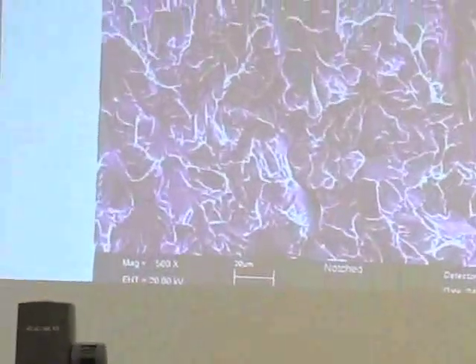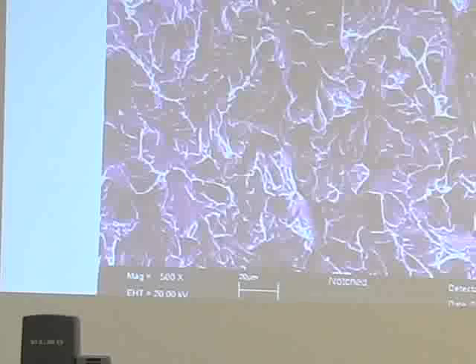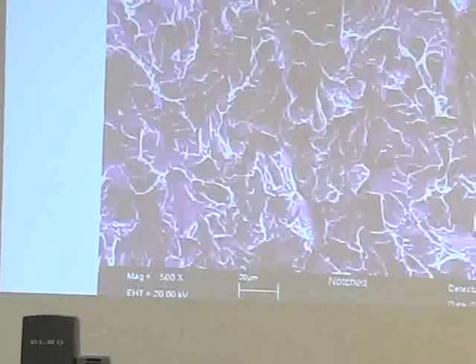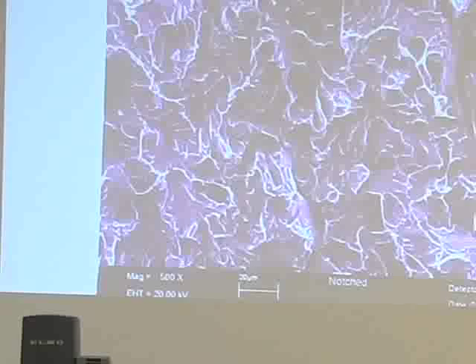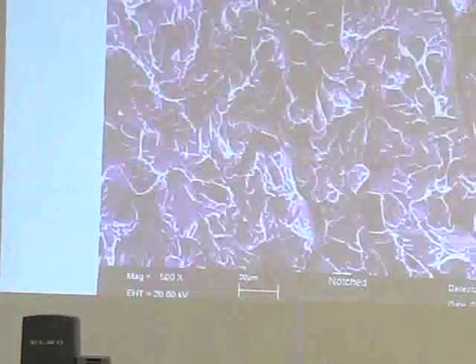Dr. Belmar kind of showed you some fractures, didn't you? You must have shown him some fractures with plane stress versus plane strain. Out towards the edge, you'll get plane stress. In the center, you'll get plane strain. Plane strain, or triaxial stress, is the worst stress condition in terms of the fracture behavior of the material. The material will change the microscopic fracture mode depending on the stress state.